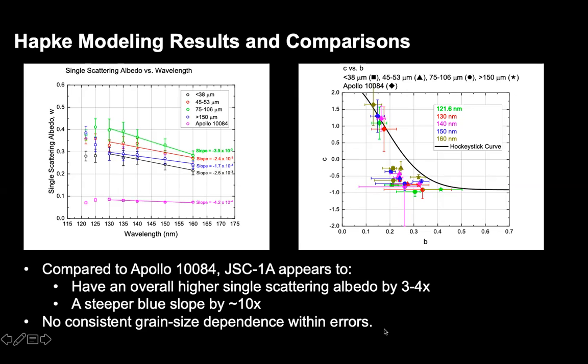One thing, though, we do have to figure out is why for these differences? Why is JSC1A more forward scattering than Apollo 10084, which is backward scattering? And why is it that there's still spectral bluing there, even though there's presence of this nanophase iron that should very much absorb, that should very much be reflective of a lot of this Lyman alpha band stuff? So there's still a lot of work to be done on that as to really why this is the case.